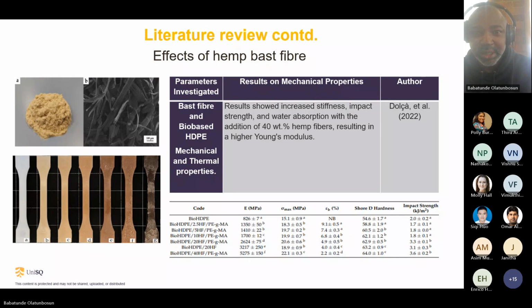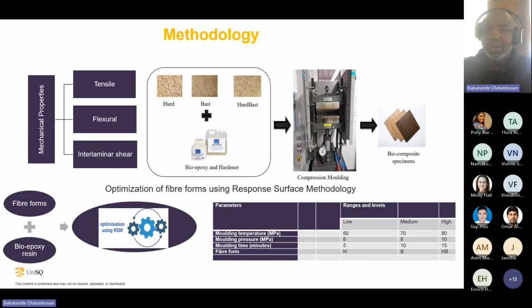Also, another researcher called Dolça et al. in 2022 actually worked on bast fiber for hemp. His result shows he used about 40% weight hemp fiber. This resulted in increased stiffness, impact strength, and water absorption. And generally, it has a high modulus. So he used a bast fiber and bio-based HDPE to look at the mechanical and thermal properties of bast fiber. In my work, I'm using sunn hemp,